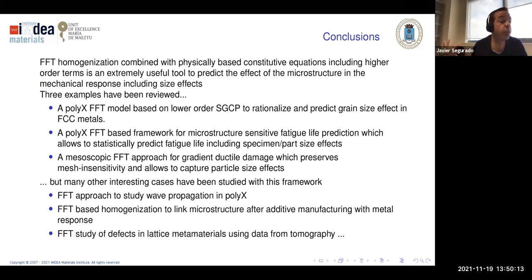And I have shown this for three cases. The first one is how we can incorporate grain size effect in a polycrystal, taking into account not only the grain size, but the whole grain size distribution and orientation, just following this polycrystalline homogenization. The second example is, again, how we can predict fatigue, but predicting fatigue not with a very simple model, but with a simulation in FFT, that allows us to include complex cases that are not easy to predict with phenomenological models, like multi-axial fatigue, fatigue with different cycles, etc. And the last example is that we can extend this to damage in order to see how ductile damage evolves and what the effect of the size of the microstructure is on the damage.